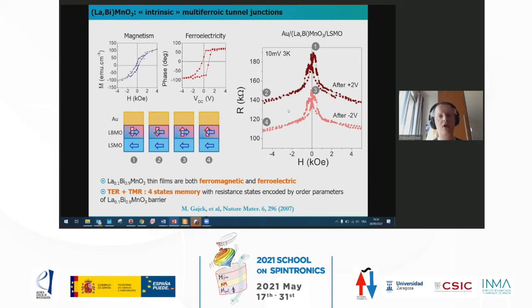And then we also saw tunnel electroresistance. You see these two curves are collected after poling the barrier in one or the other ferroelectric state. So we had a 4-state memory in which the 4 resistance states were encoded by the 2 order parameters of the multiferroic barrier. So this was probably the first spintronics multiferroic device, really at the beginning of the booming era of multiferroics.